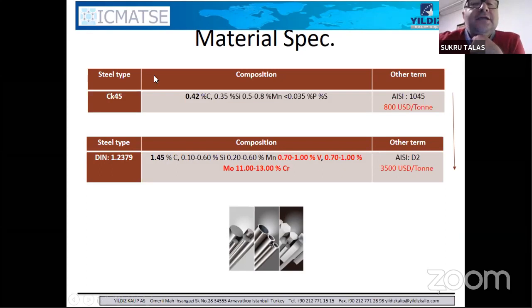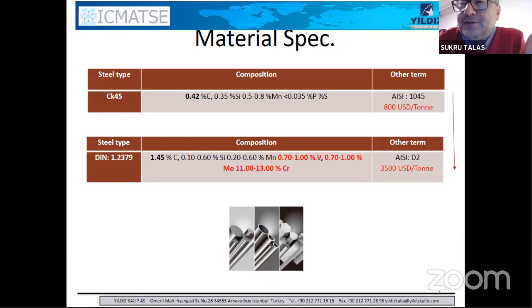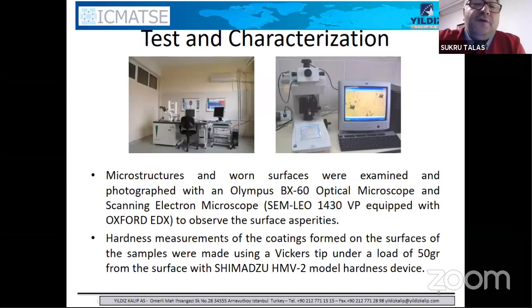Anyway, these are the steels. As you can see, the CK45 is $800 per metric ton, and the steel that we replaced, 1.2379, is $3,500 per ton. So we are making very good use of this process if it works, because the other steel is very expensive. In this table it says $3,500, but when you're cutting and selling them separately, it becomes $6, $7 per kilogram. So it's very expensive. So what we did, we did metallurgical analysis on the specimens using an optical microscope and an electron microscope. We also measured the hardness of the surface.